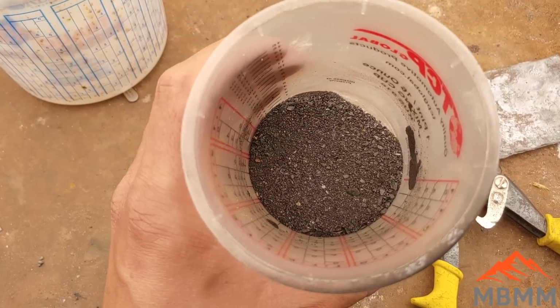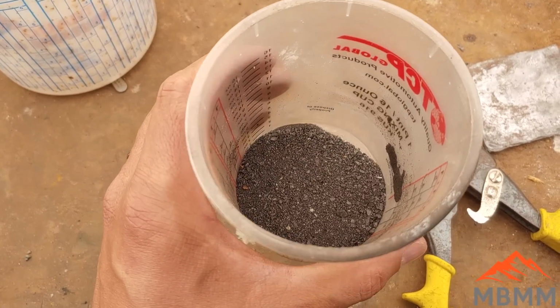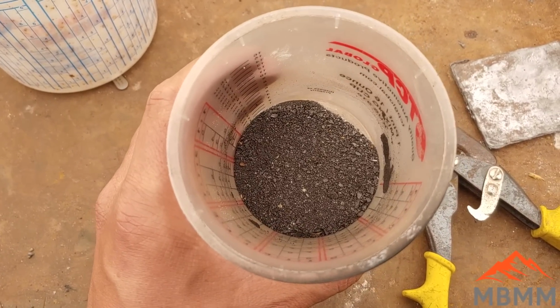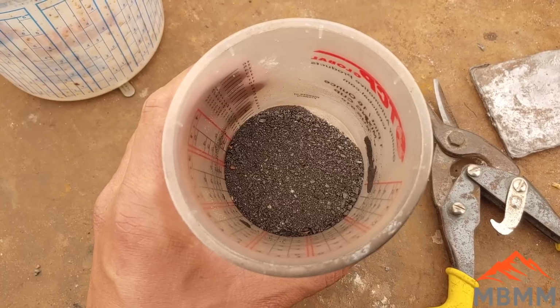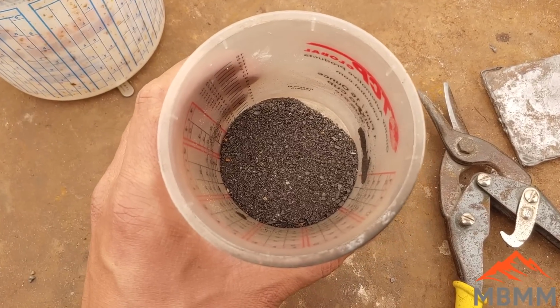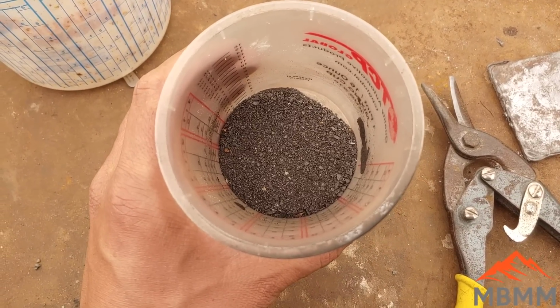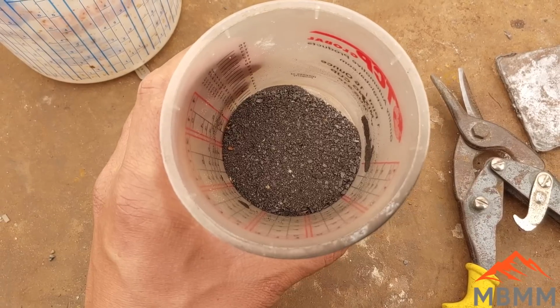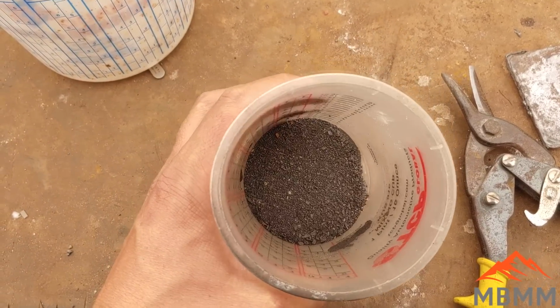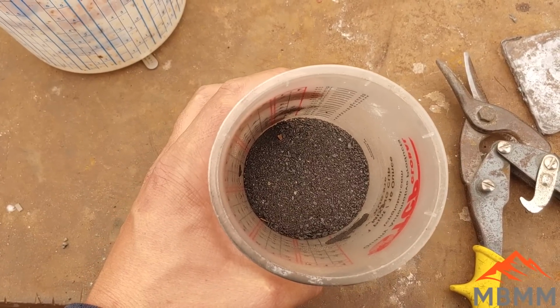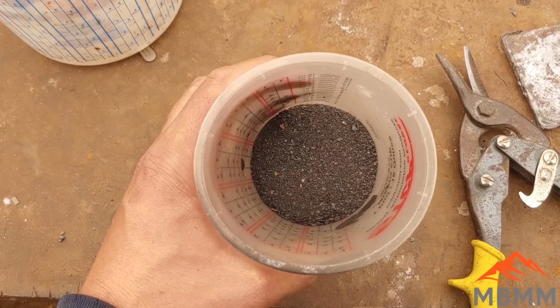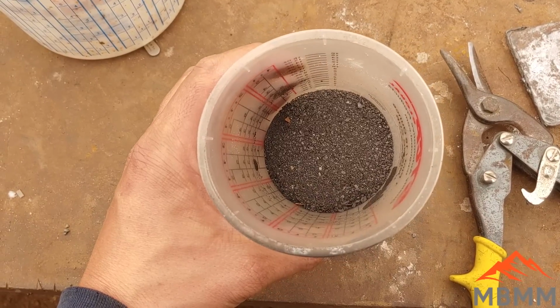We're going to do a little assay now, just to see if there's any more precious metals in there. And I have 100 grams here, so I'm going to mix twice as much flux as I normally do. I'm going to do 200 grams of anhydrous borax, 200 grams of lye, and 100 grams of silica sand. We'll smelt it and add a little lead for collector and see what we can get out of this mat.